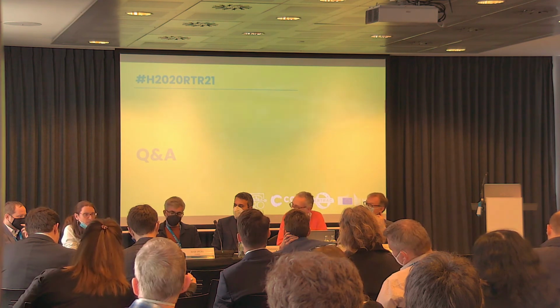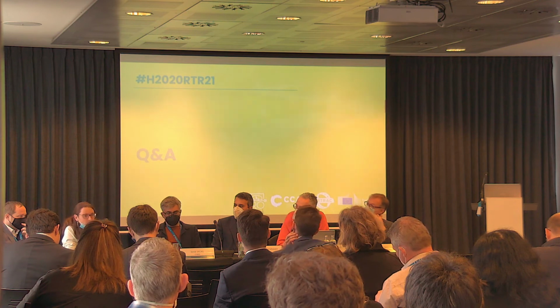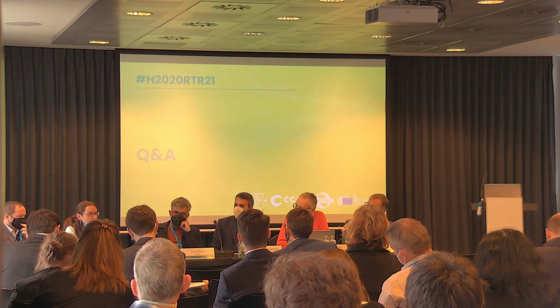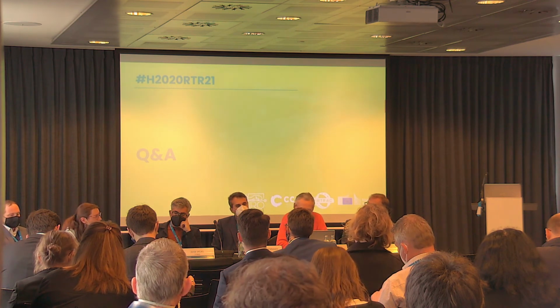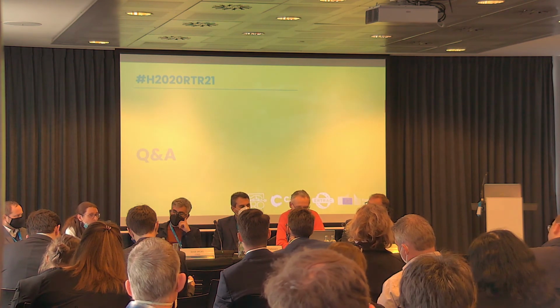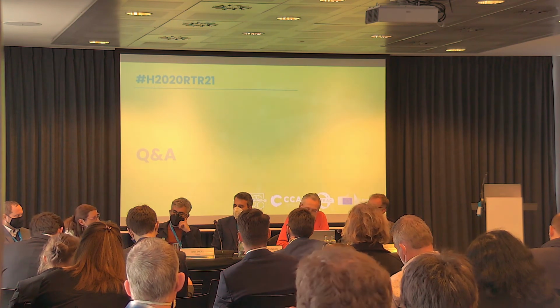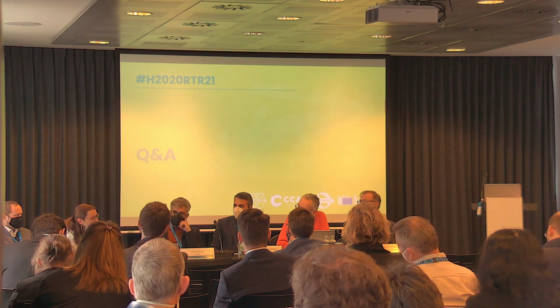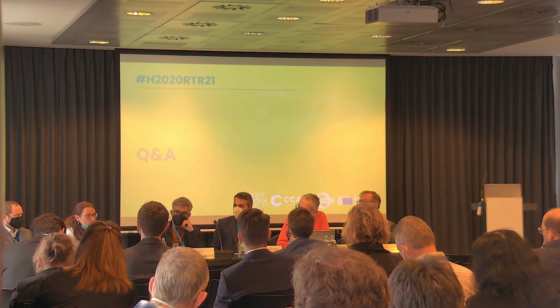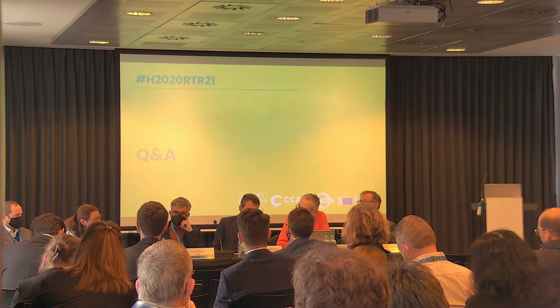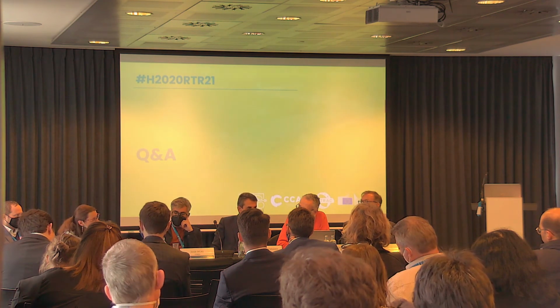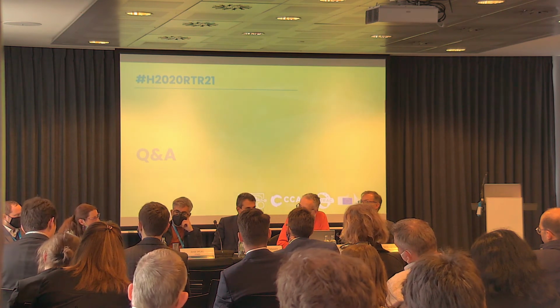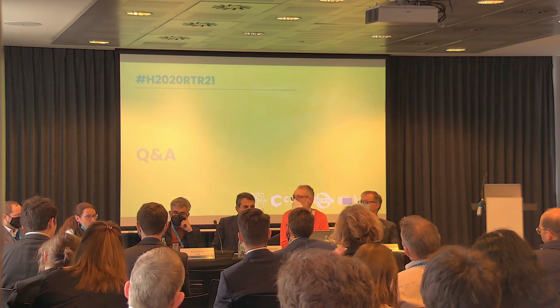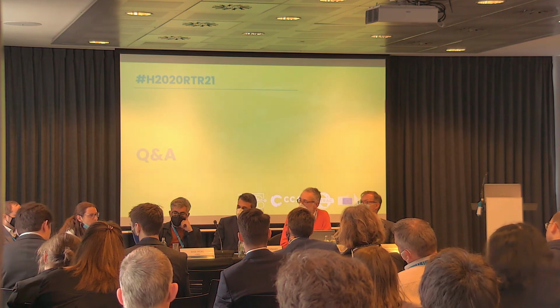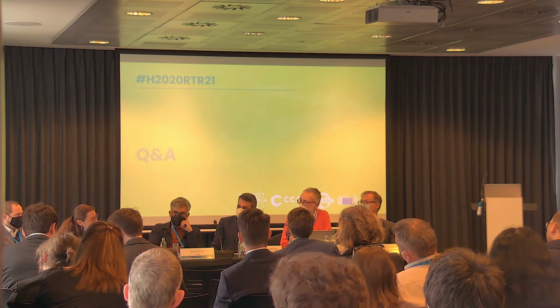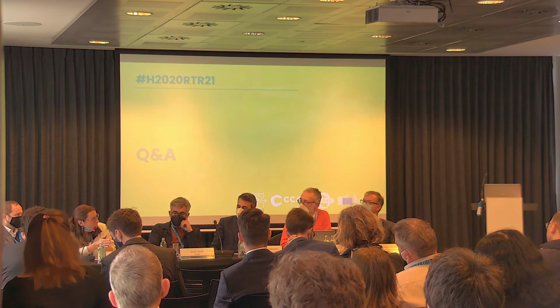Well, thanks for the question. The challenge for us was the stability of the anode, because we all know that silicon has many issues, the most important being the volume expansion. But the innovation we brought with this project is that our core, the copper silicide nanowires, are coming directly from the substrate. So it's a very stable structure when we are depositing the amorphous silicon. And the advantage of the nanostructure is not only that the active material is perfectly anchored to the substrate, but also, with this porous core, when we are depositing 1 mg, unfortunately I didn't show the image, we are still having enough space between the different nanowires, even after 1 mg per square centimeter deposition.